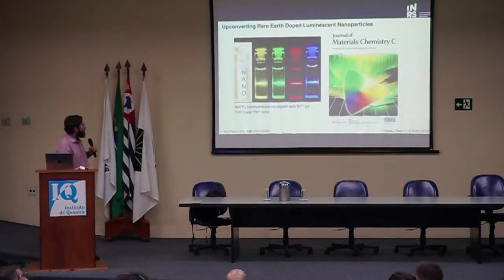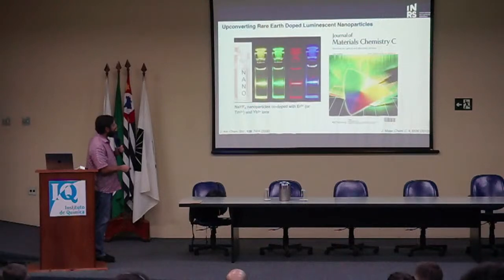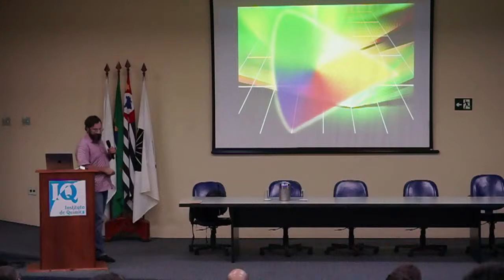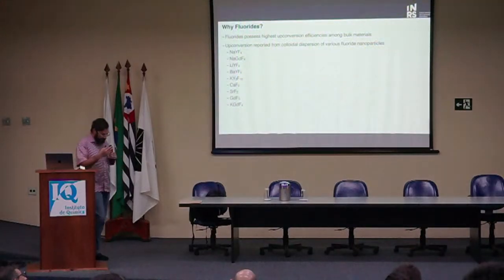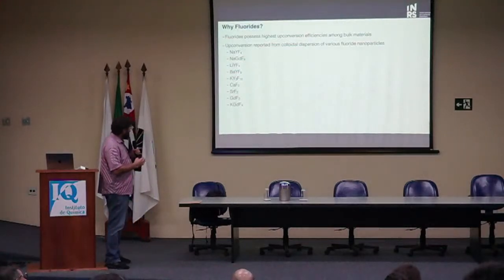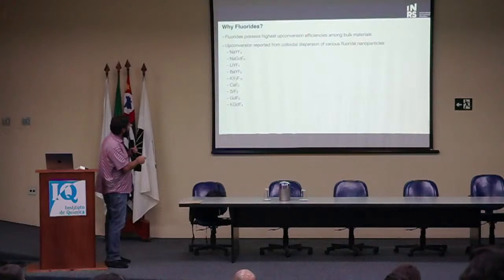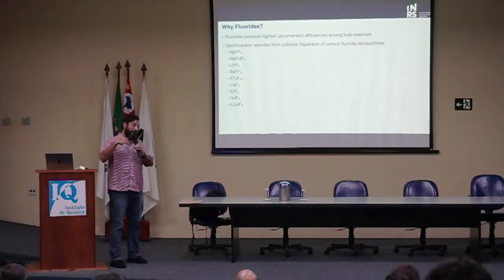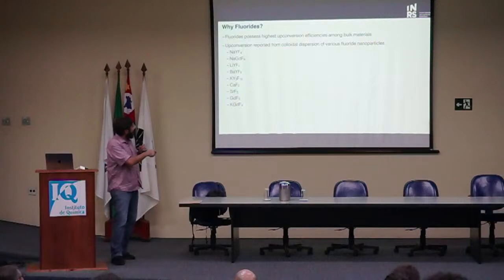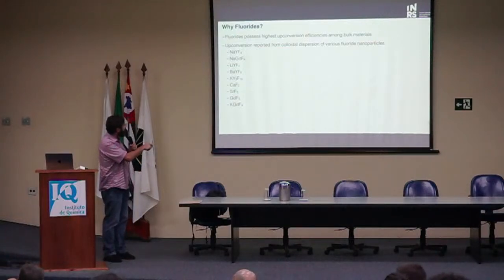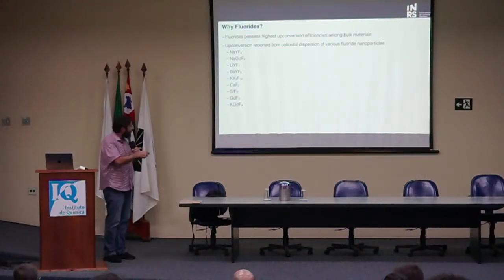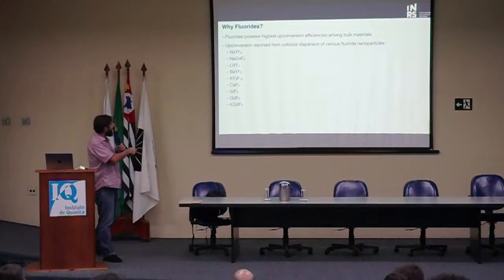So we can get all the colors of the rainbow. We do it differently than the quantum dot people. We change the dopants, we co-dope, we change the concentration of dopants, and so we can pretty much get all the colors up to white light, just by playing with this concentration. I also want to mention that we work principally with fluorides, okay? And I need to mention here that the rare earth ions are dopants, okay? So the nanoparticles are not based only on rare earths. The rare earths are kind of impurities that we intentionally place inside these crystals, and they replace the metal stoichiometrically inside the crystal, okay?